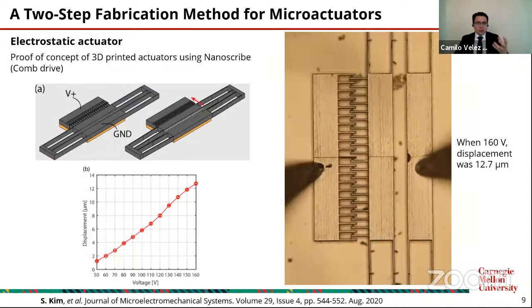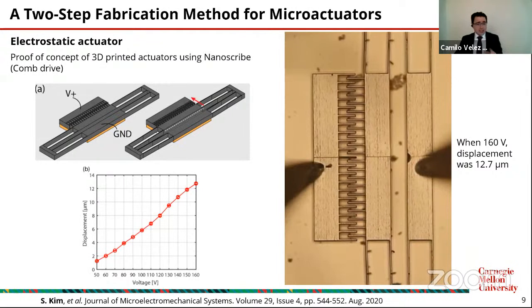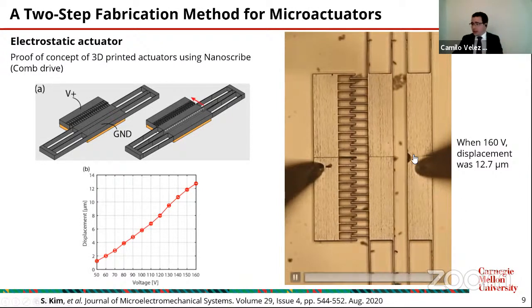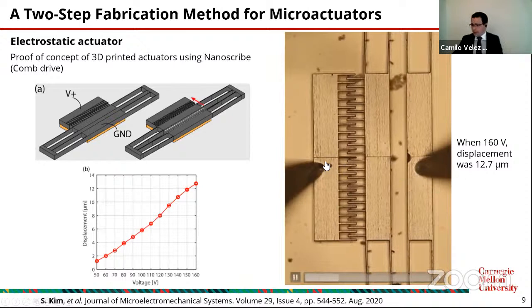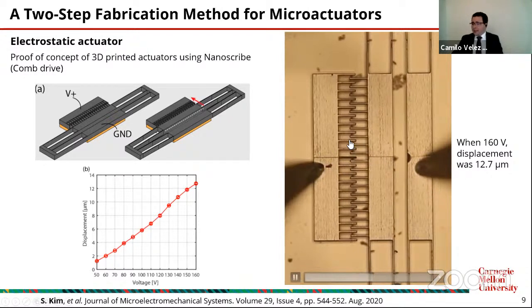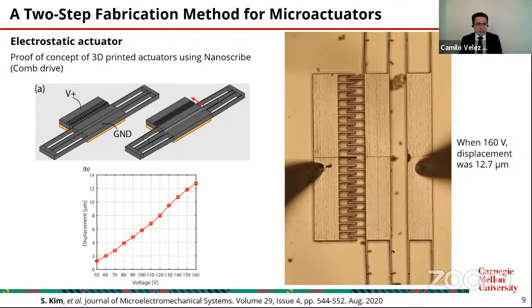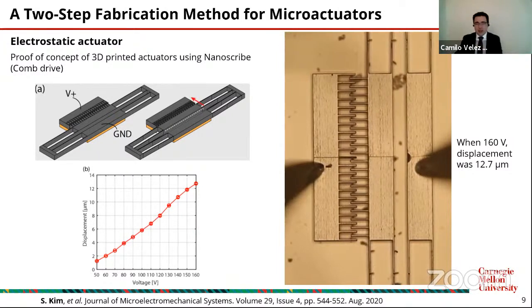We moved a step forward and tested electrostatic actuators. So in this case, you just apply an electrical field between these two ports, and there is going to be a capacitance on those fingers. It's a common microelectromechanical systems technique. And you generate electrostatic force that attracts this comb drive, as we call it. And we can generate displacements of around 12 micrometers, of course with higher voltages than the other one.